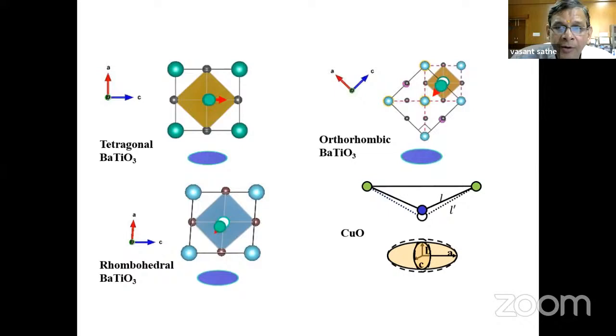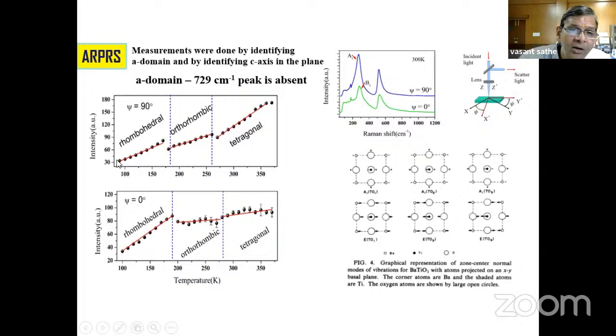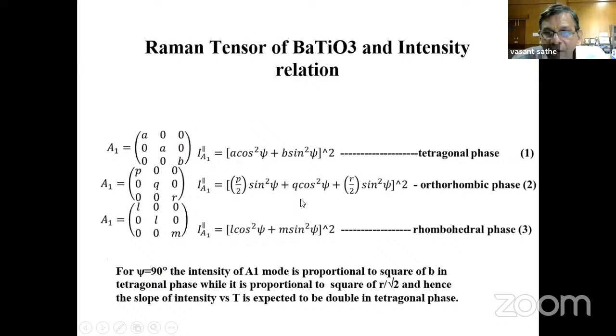In the orthorhombic case, you can see the polarizability is going to change in two directions. And in rhombohedral, we know the displacement is along the 111 direction. So you take any geometry, and you should get the same results. And this is a very remarkable experiment. You can see in the rhombohedral case, the slope is the same whenever we change the geometry of the experiment. While in the tetragonal case, when we are sensing this polarizability, we could see the intensity falling linearly like this as the polarization falls, while here it is nearly the same. Anyway, I'm sorry that I could not explain it much to you because of time constraints.